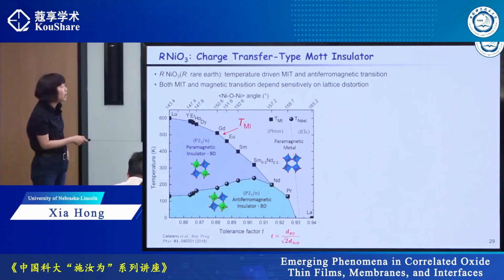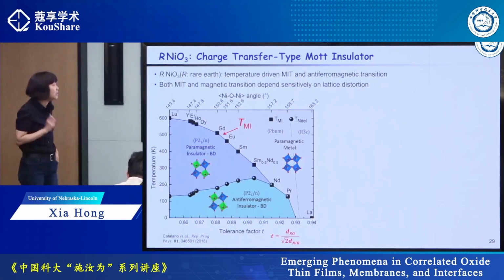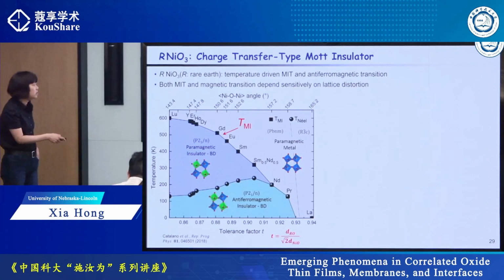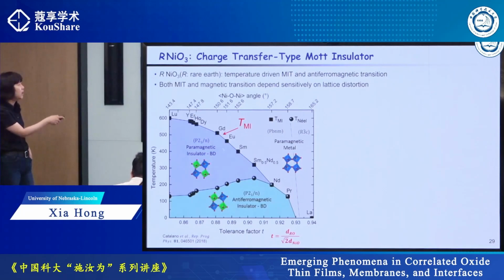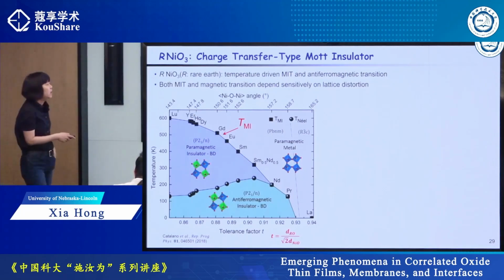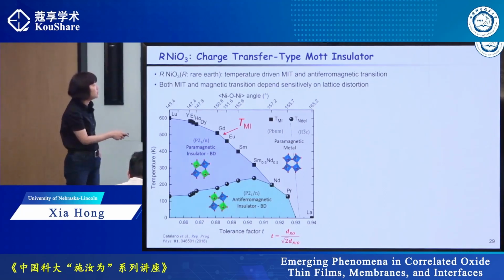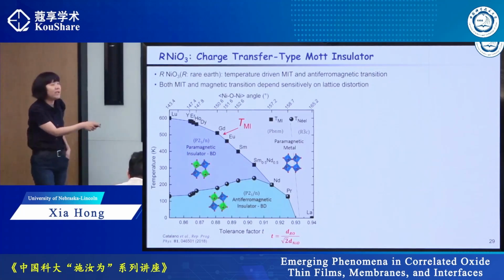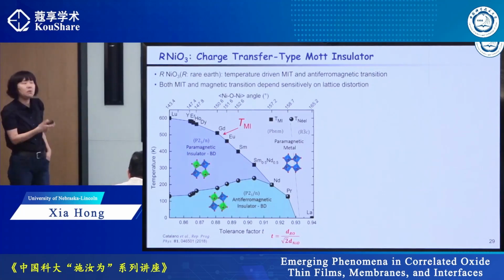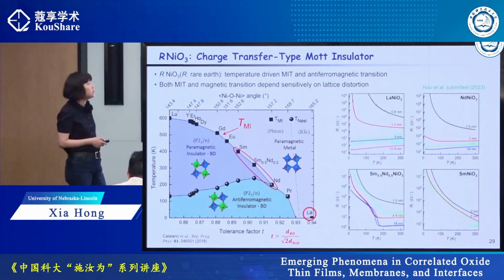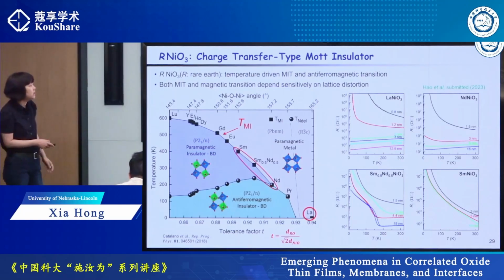So we have one element, lanthanum. Lanthanum nickelate is metallic because it has a very high tolerance factor. With reducing tolerance factor, the sample changes to insulating state and the TMI increases. For some of them, the metal insulator transition and the magnetic transition are coupled, but then it starts to deviate. So we studied 4 different nickelates with different TMI. I want to see what effect they can produce.